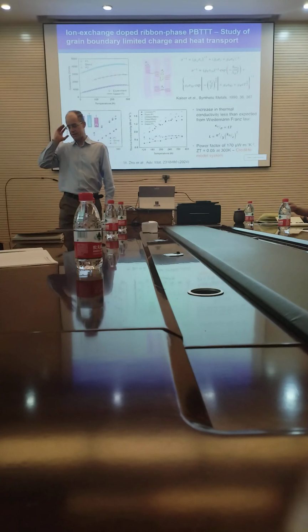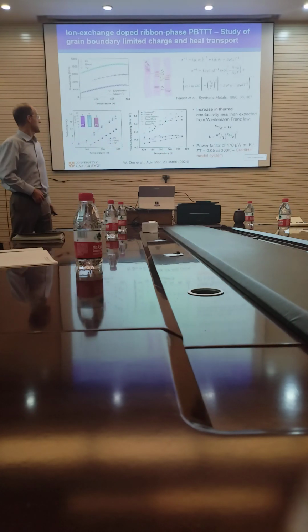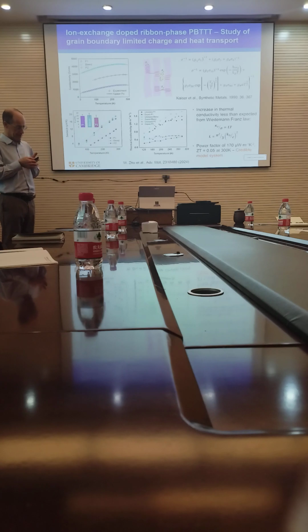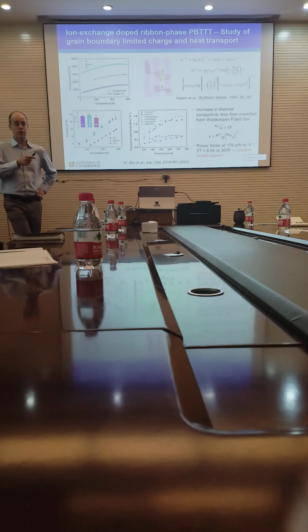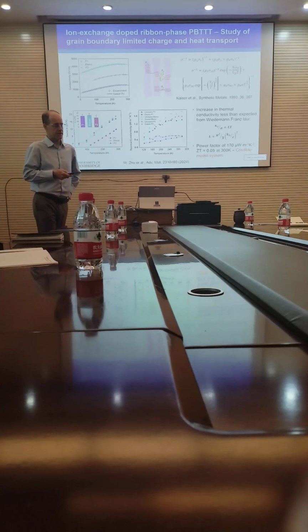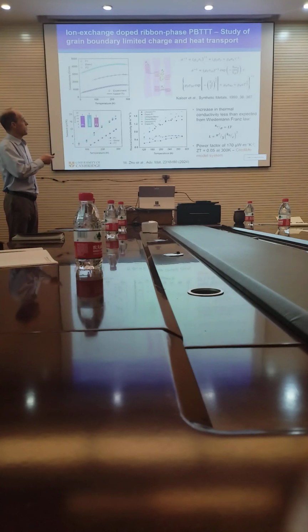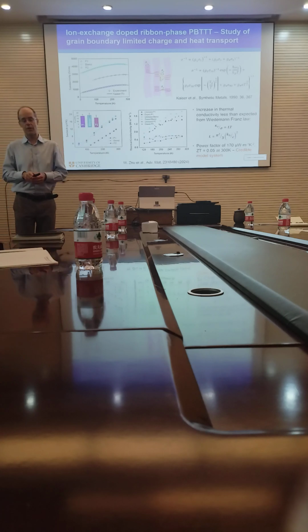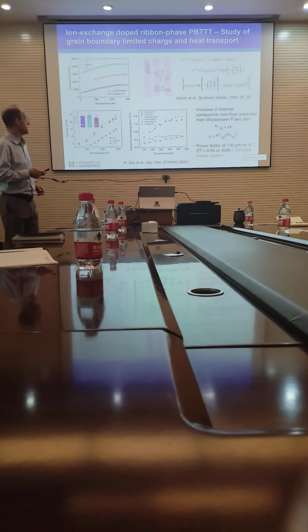So we now have a model system where we can study the thermoelectric physics, and I don't want to discuss it in too much detail because I want to move on to something else. But we've, for example, been able to establish, by looking at the temperature dependence of the conductivity and fitting that to a grain boundary model, that indeed, as we incorporate these tie chains, we can reduce the grain boundary resistance.